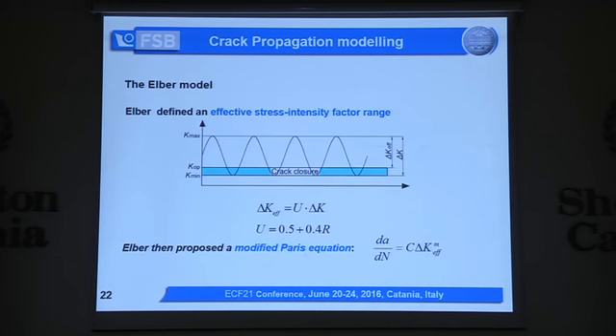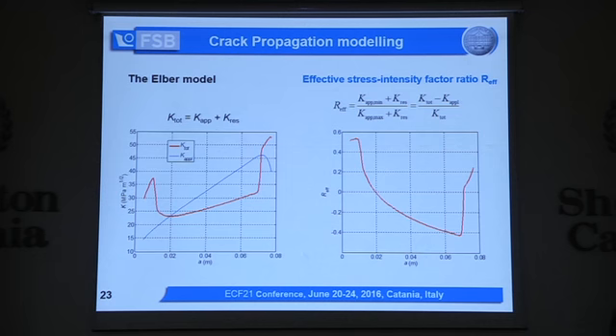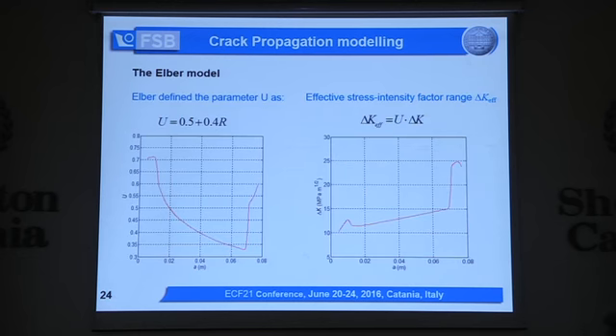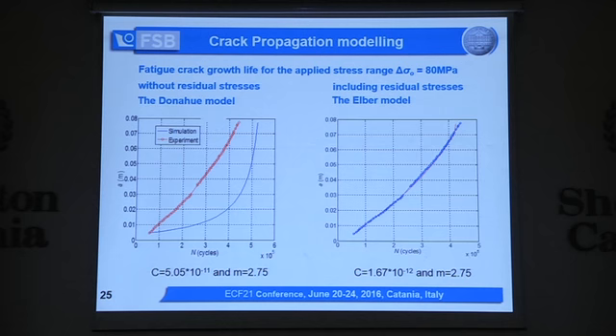And we used Elber model, which you know very well from the literature. And in the Elber model, we need R ratio. That's local R ratio, which depends on K maximum and K minimum. So this is this, and U function depends on this R ratio. And then we have effective stress intensity factors, and as explained before, by integrating Paris equation and this delta K effective, we can simulate fatigue life. So without considering residual stresses, we have this, what we have seen before. And with considering residual stresses, simulation fits quite well to experiment, maybe even too well, too good agreement.